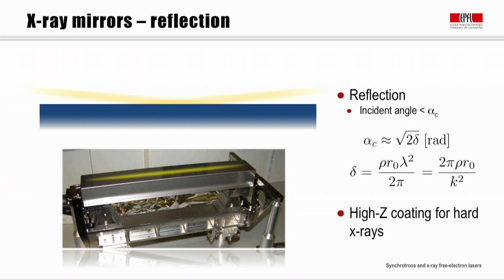Normally, fabrication of the X-ray mirror is limited to approximately a meter or less. This overspill problem is resolved not by making longer and longer mirrors, but instead by coating the mirror. The mirror is almost always made either from silicon or fused silica glass, and the coatings are some high-density material, most commonly rhodium and/or platinum. And this bumps up the critical angle, which, we've just reiterated, is proportional to the square root of the electron density.